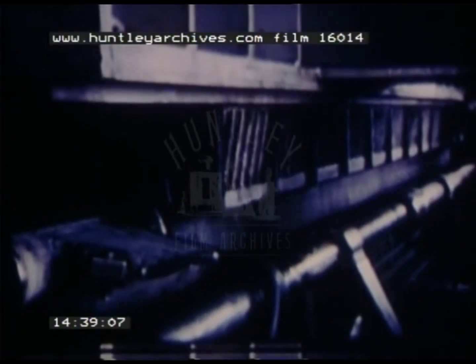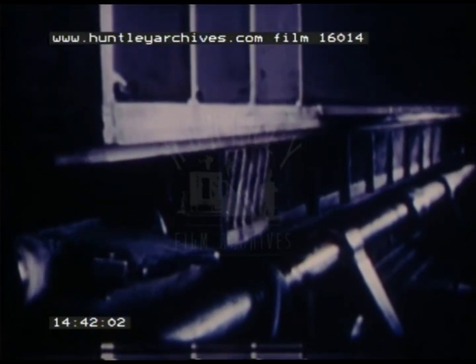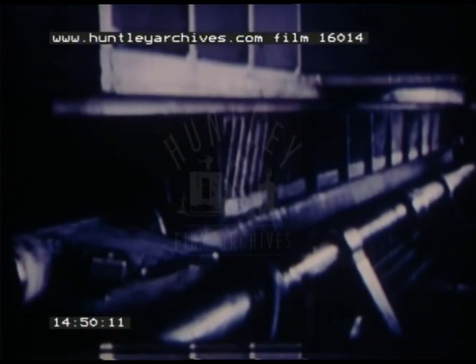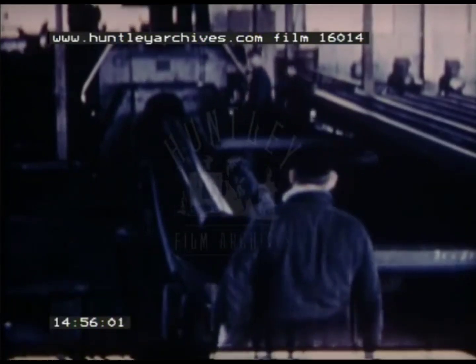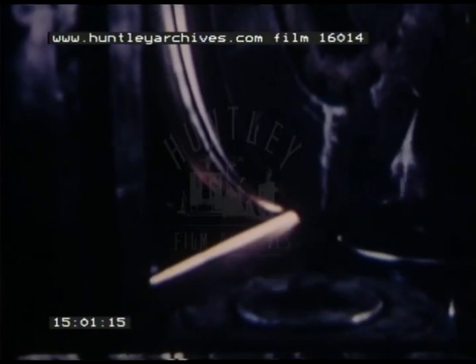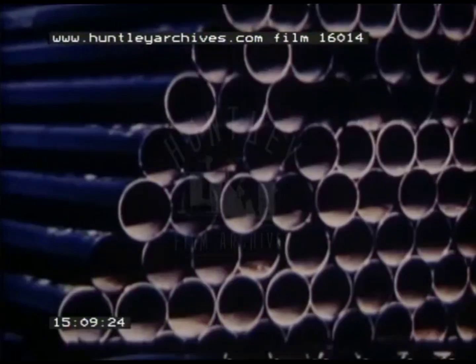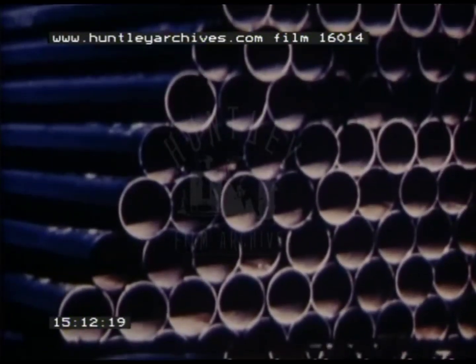Accurate circular form is achieved in this hydraulically operated press, which compresses the plate between the upper and lower dies. This cold working of the steel, incidentally, changes the physical structure to give it additional strength to withstand the high internal pressures that are built up in oil and gas pipelines. Large circular electrodes conduct electricity, which heats the edges of the seam until they are near molten. Pressure rolls fuse the edges into a strong, true weld. After final inspection, the pipe is buffed and protected with a weather-resistant prime coating. And so today, Western pipe is moving in ever-increasing tonnage to markets once claimed by Eastern mills.